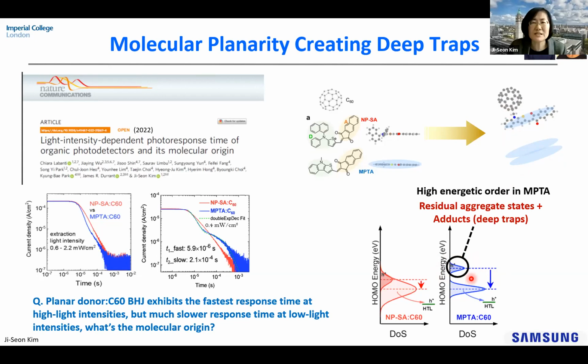Those, either intermolecularly formed excitonic states or adduct states, can induce lower energy subgap states. So when you operate your device at low light levels, these trap states can be very problematic. At high light, the planar molecule gives a much faster transient photocurrent. But when you lower your light intensity, it actually produces a much slower transient. So your image sensor, for example, your mobile phone, when you operate under very low light, will produce very slow turn on and off characteristics, which is undesirable for the device. So we have to be quite careful when we design the molecule.